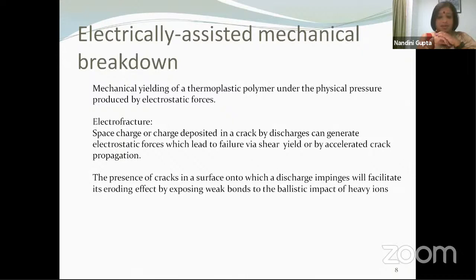The presence of cracks in a surface onto which a discharge impinges will also facilitate its eroding effect. So suppose, as I said yesterday, there are situations where we have dielectric materials used in the vicinity where we accept a lot of discharge to happen, or maybe some kind of radiation to happen. Now, if you already have cracks, the electric fields on the surface of this material will be considerably modified, and there would be stress enhancement in small regions. So when you have any discharges impinging on the surface, the cracks will lead to failure. So these are situations where you have electrically assisted mechanical breakdown. Your material can break either mechanically or electrically, but these processes will act in synergy and aid each other and lead to breakdown.